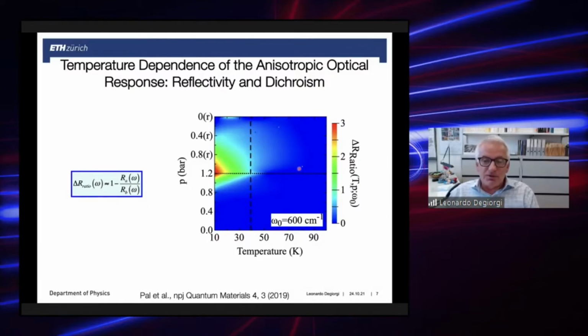And you observe, in fact, that you need to cross TC to go into the superconducting state to have a stress-induced optical anisotropy, which, however, turns out to be fully reversible by sweeping the external symmetry breaking field at any temperature. So even though there is some experimental evidence for a substantial nematic susceptibility, and therefore for nematic fluctuations, also above TC, this seems to be rather weak from the perspective of our optical investigation to be clearly detected. If they are present, they seem to be very, very weak or somehow negligible.